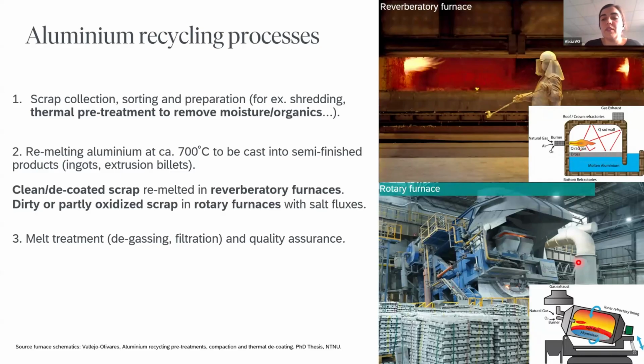And then we have the second alternative that would be using rotary furnaces. We have the cross section here, and they use significant amounts of salt fluxes. And this method is more common for a scrap that is contaminated, that has not been decoated, or a scrap that contains a relatively high amount of oxides, since the salts help removing and separating the oxides from the metal.